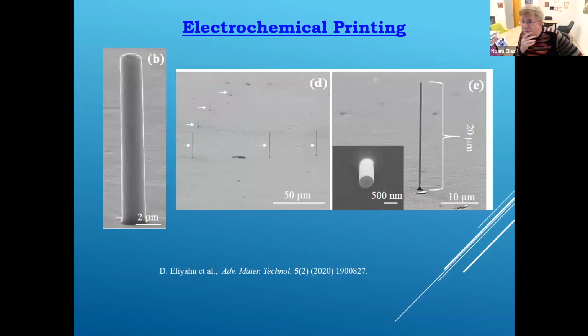I mentioned that we are developing in my lab electrochemical printing. So this is not powder bed. What you can see, this is copper. We started with copper simply because electrodeposition of copper is well known. What you can see, self-supported columns, and the substrate here is a sheet of copper also that was polished down to 0.05 micron. Look at the surface roughness, how the surface of the substrate looks compared to the surface of this pillar. There is absolutely no additive manufacturing technology to date that can give you such a fine surface roughness.